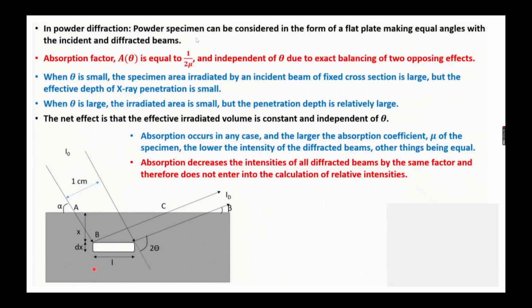So in powder diffraction, the powder specimen can be considered in the form of a flat plate making equal angles with the incident and diffracted beams. I naught is the intensity of the incoming wave, and this is the diffracted beam, with an angle of 2 theta. They have shown some calculation and derivation, but the main thing is the absorption factor is equal to 1 upon 2 mu. Also, the absorption decreases the intensity of the diffracted beam by the same factor, and therefore does not enter into the calculation of relative intensity.